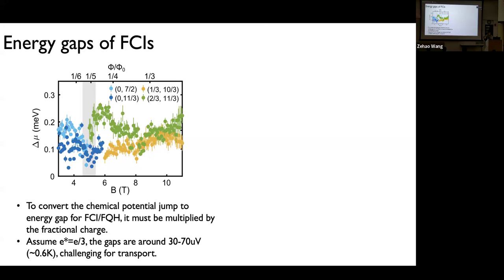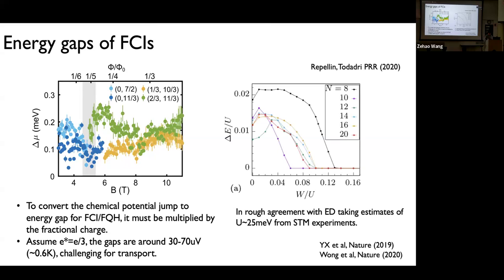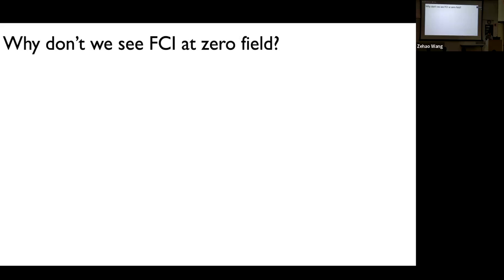And you can imagine it could be quite challenging for the transport experiment, especially, it was mentioned yesterday, all these samples, they have actually a lot of what's called a twist angle disorder. So here I'm just showing you the ED estimate again. The number that you will get in the perfect case would be 250 microvolt, but in real life you have a lot of things that you don't want.